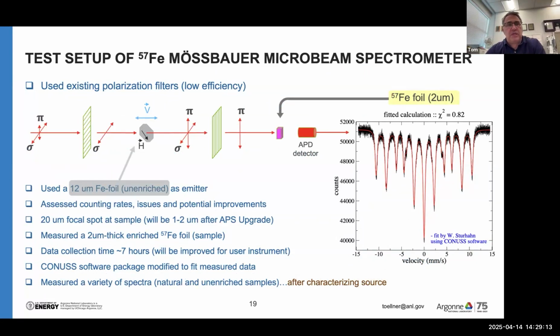To test this setup, I put together a little test setup prior to the APS going down for the upgrade. This was not optimal, so counting rates were quite low, but it basically employed everything I needed to find out where some issues might be. In this case, I just used a 12 micron unenriched iron foil, and I put that on a Mössbauer drive and put them between 2 linear polarization filters. The sample was an iron-57 foil, 2 microns thick. This is 95% enriched, and we collected. This spectrum took 7 hours to collect. That's a long time because the counting rates were low.